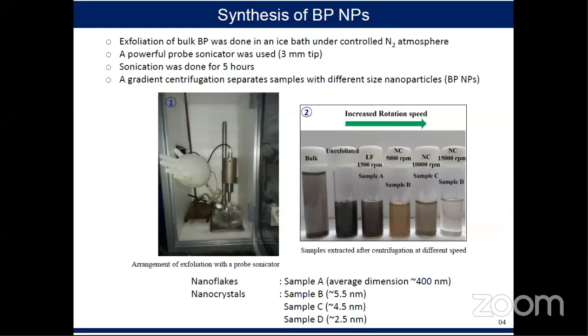Please continue. Okay. So after the successful exfoliation, we centrifuged at different speeds: 1500 RPM, 5000, 10,000, and 15,000 RPM. We gave the sample names A, B, C, and D respectively. After microscopic analysis like HRTEM and atomic force microscopy, we found that sample A nanoflakes have an average size of 400 nanometers, and samples B, C, D are essentially nanocrystals of average size 5.5 nanometers, 4.5 nanometers, and 2.5 nanometers respectively.